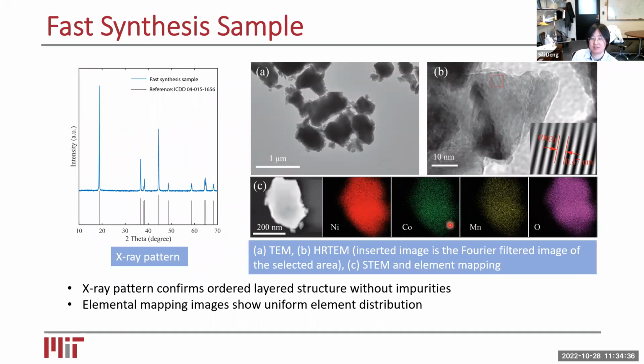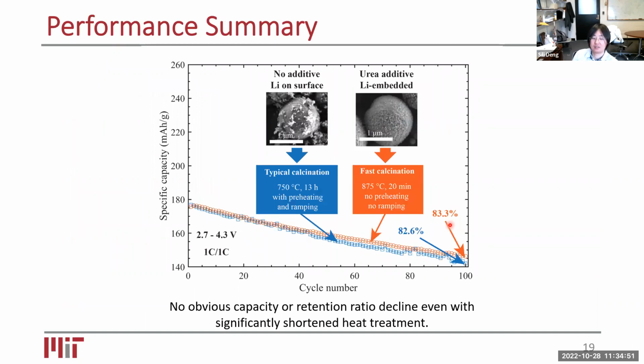Quickly, I'm going to show that some further characterizations demonstrated indeed we're getting the desired crystal structures with uniform distribution of all the elements of interest. Performance-wise, this is not the best performance we get, but with the traditional method, you cannot get even better performance. So we just pick one case that matches the performance of the without additive case. Both of them have comparable performance, but you can look at our synthesis time and annealing time, our annealing time is significantly shorter.